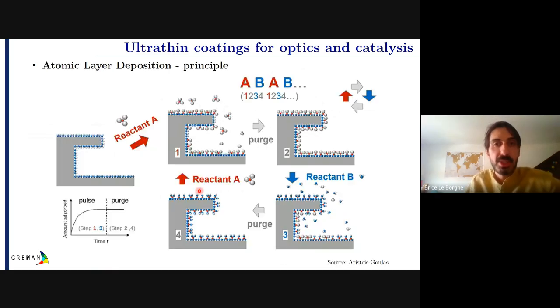But for our application, I think ALD is good. So ALD, to quickly present it, is a chemical reaction with the substrate. So when you have a substrate that can have cavities, you necessarily have chemicals at the surface. And first, to do an ALD cycle, you first pulse a reactant that will be adsorbed at the surface of this material. Then you have a purge cycle where you remove all the species that didn't react with the surface.